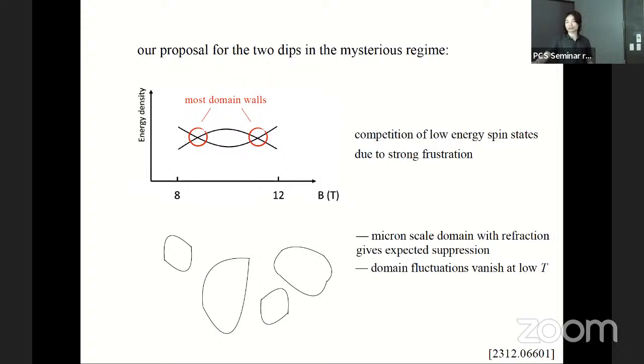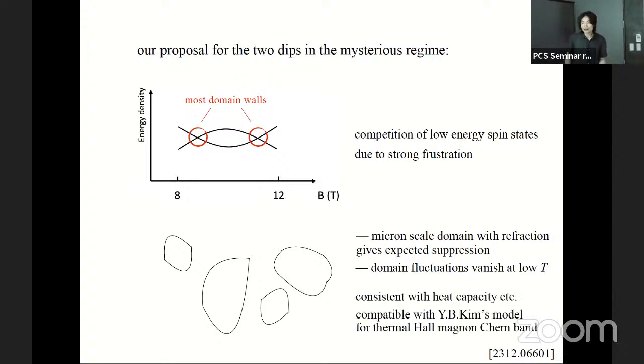And moreover, it's consistent with the fact that these two dips go away at low temperature, right? So these two dips come from when the two energies are closest. In that case, there will be the most domain walls. And the two dips will become harder to see at low temperature because as the temperature becomes lower and lower, the thermal fluctuation becomes smaller, so there will be fewer domain wall fluctuations. So this is consistent with that. Moreover, it's consistent with other experimental data, such as the heat capacity. Because now you have the thermal fluctuation of the domain walls, then you need to care about their thermal capacity contribution, and we found it's also consistent with the data.